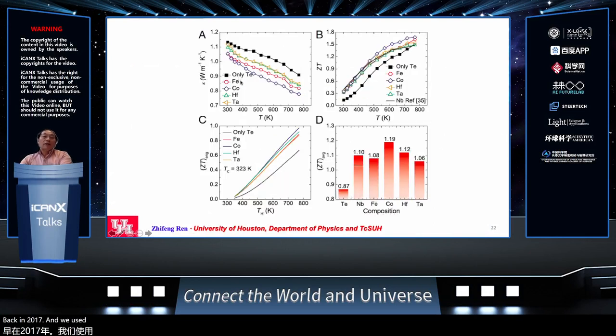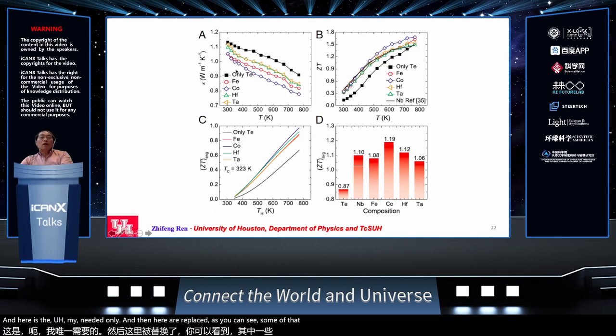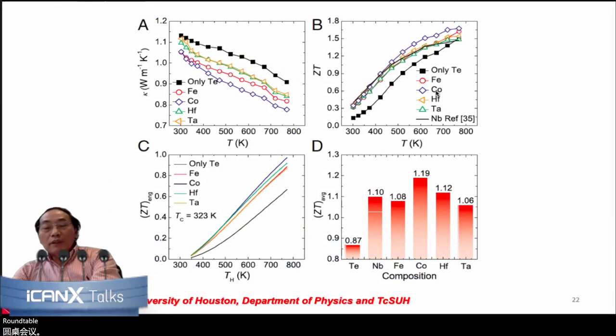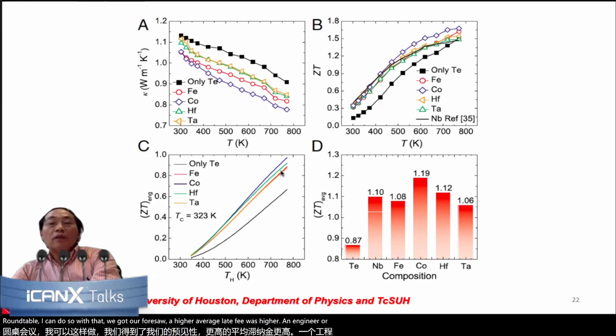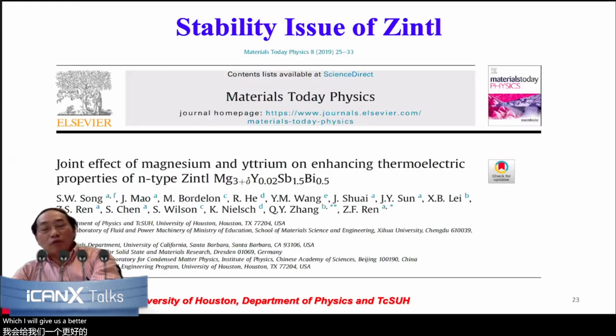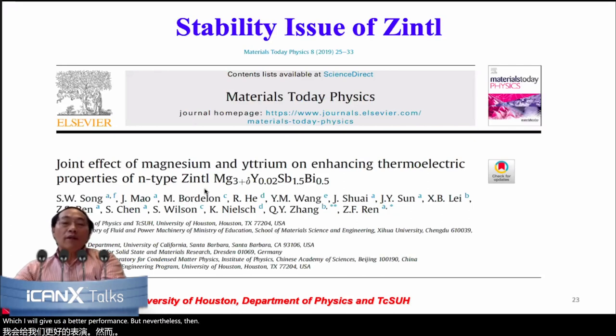And we used a lot of other elements like iron, cobalt, hafnium, tantalum to partially replace the magnesium. And here is the magnesium only, and then here are the replaced ones. As you can see, the thermal conductivity got reduced in all of them, and the power factor was maintained, even improved a little bit. So the ZT improved over the whole temperature range, from room temperature to high temperature. With that, we got, of course, a higher average ZT, also a higher engineering ZT, which will give us better performance.